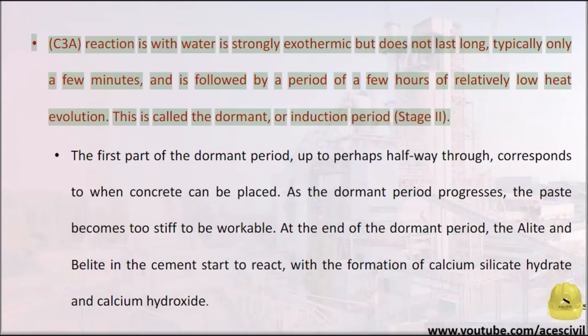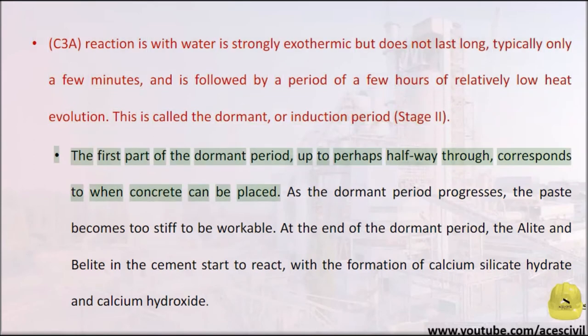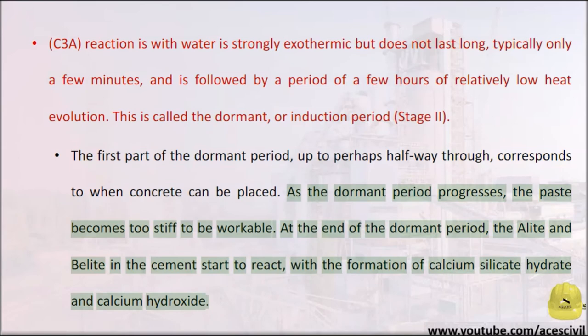C3A reaction with water is strongly exothermic but does not last long — typically only a few minutes — and is followed by a period of a few hours of relatively low heat evolution. This is called the dormant or induction period, Stage 2. The first part of the dormant period, up to perhaps halfway through, corresponds to when concrete can be placed. As the dormant period progresses, the paste becomes too stiff to be workable. At the end of the dormant period, the alite and belite in the cement start to react, with the formation of calcium silicate hydrate and calcium hydroxide.